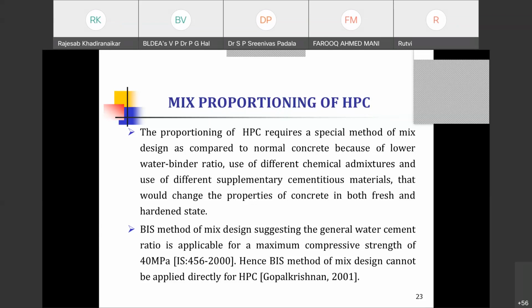So you have to study all those things, and then accordingly, you have to choose a proper superplasticizer, and ensure that it produces a very dense concrete with a low permeability, and it minimizes the effect of heat of hydration, and then produces a concrete with a low air content. Sometimes there are some plasticizers which induce higher air content. That will be a problem. Then it should allow you to go for a lower water cement ratio.